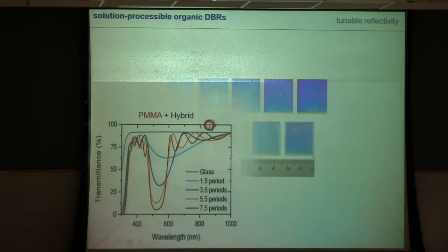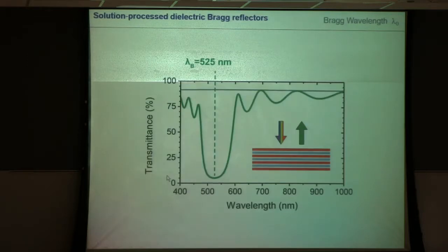But what you see nicely is when you increase the amount of layers, so the glass here in gray, and then you add more and more half periods, so here 3.5 periods, etc., you nicely see what we call the stop band coming up, the stop band where light is reflected. It is relatively narrow. The reason is the refractive index contrast between PMMA and the hybrid. Since we have polymers, we can easily solution process it. And what was also surprising to us, it's very, very accurate. We can very much define where the Bragg wavelength is. That's the center of the stop band.